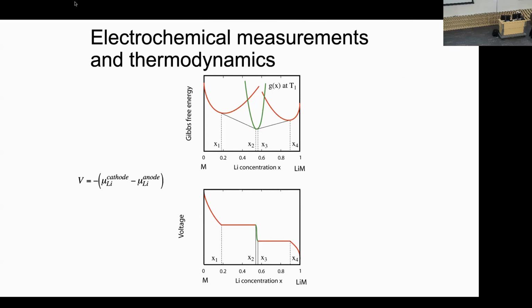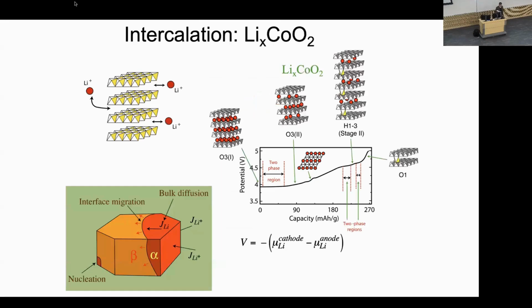And so just by inserting lithium and then removing it back and looking at the voltage curve, what you're really doing is you're kind of sweeping through the binary phase diagram. And by looking at the voltage, you can kind of already sketch out what this phase diagram is going to look like, because you have direct access to the chemical potential.